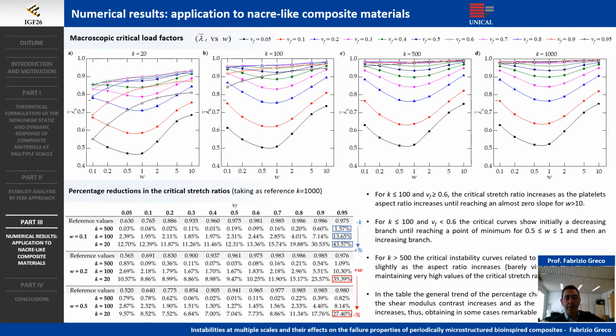The macroscopic instability curves are now reported as a function of the platelets aspect ratio W for a wide range of volume fractions. We can observe that for the cases with low shear modulus contrasts, the critical stretch ratio increases as the platelets aspect ratio increases until reaching an almost zero slope for W equal to 10. While for low platelets volume fractions, the critical curves show an initially decreasing branch until a point of minimum is reached, and then an increasing branch.